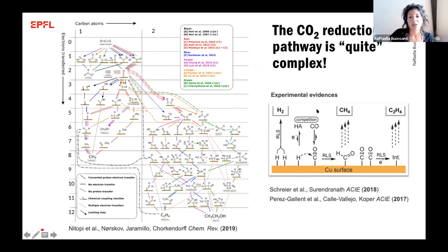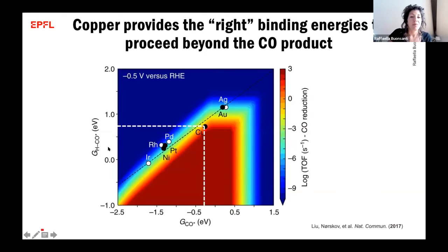Now, this comes from theory, and experimental evidence is trying to pinpoint the most important intermediates. So far, we know that, for example, the formation of CO is important, as well as the formation of CHO for the production of methane, and eventually that C-C coupling must occur to form ethylene. Now, if we plot on this graph the binding energy of two of the intermediates that I've just mentioned, namely CHO and CO, here we have surfaces of different metals.